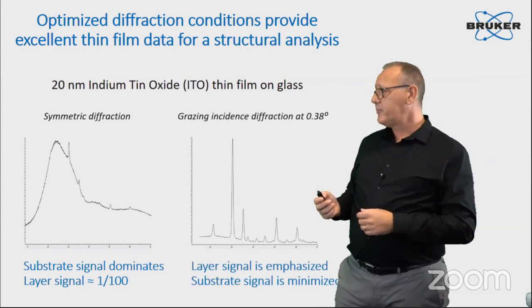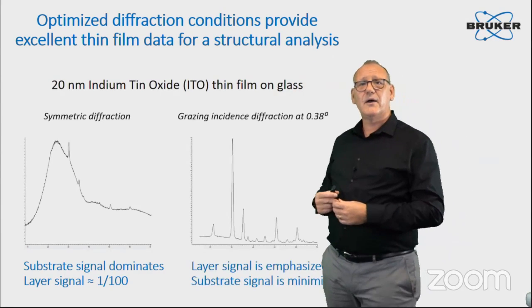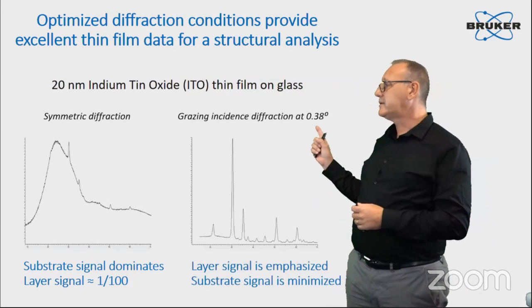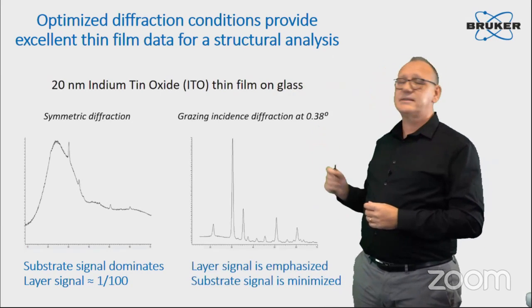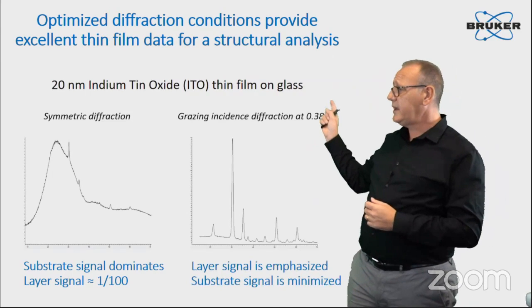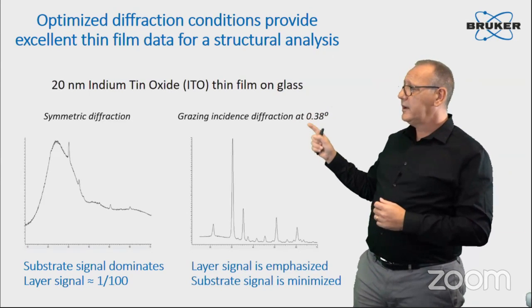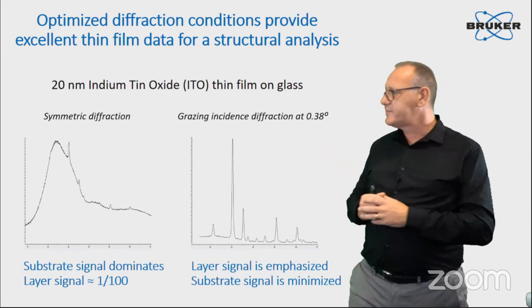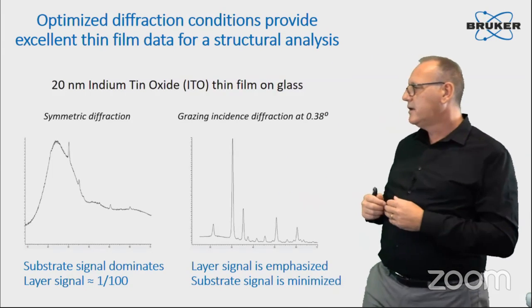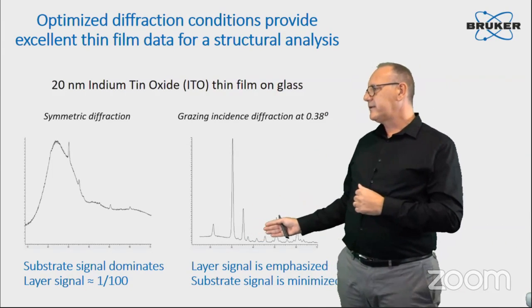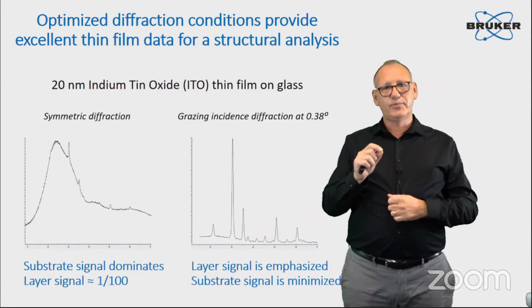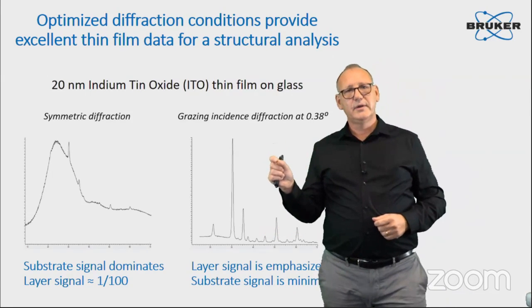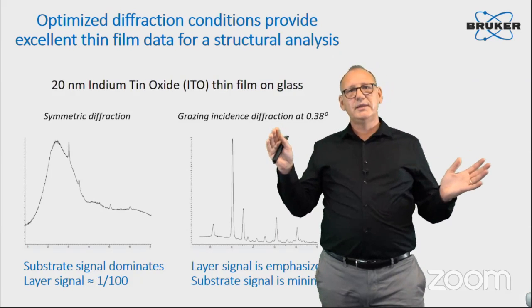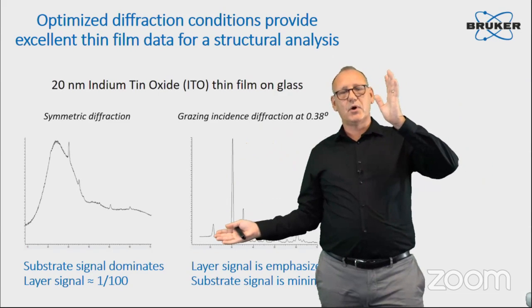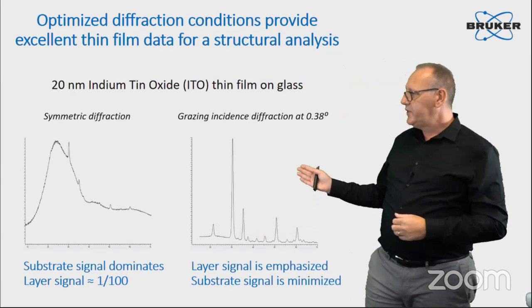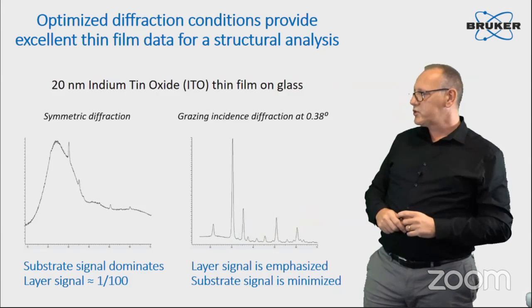If you now set up an extremely precise GID measurement at a selected incident angle, and this incident angle is determined by optimizing the penetration depth of X-ray with some alignment scan, look at the scan you can get. This is the exact same sample on the exact same machine. You simply have changed the relative position of tube and detector. So this is the appropriate way to measure thin films.